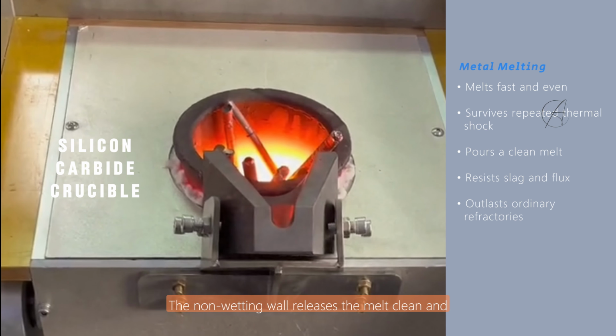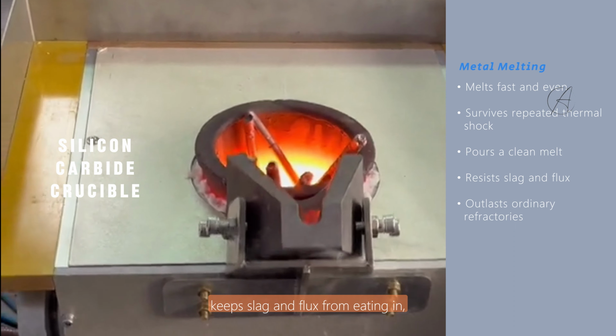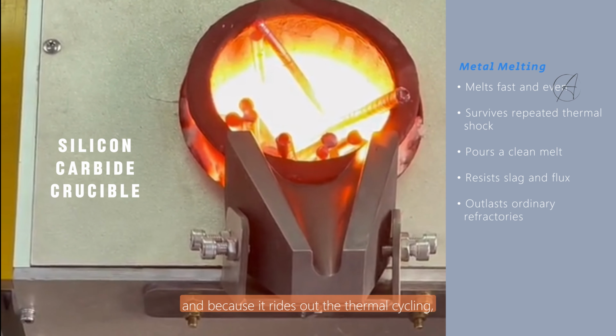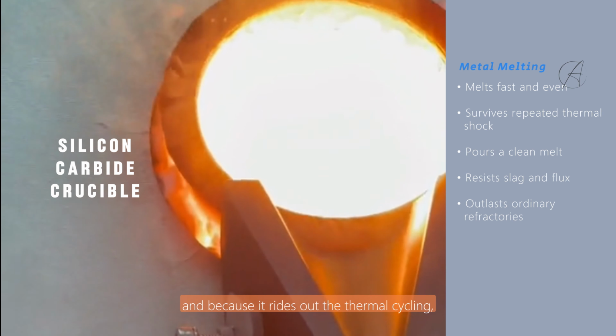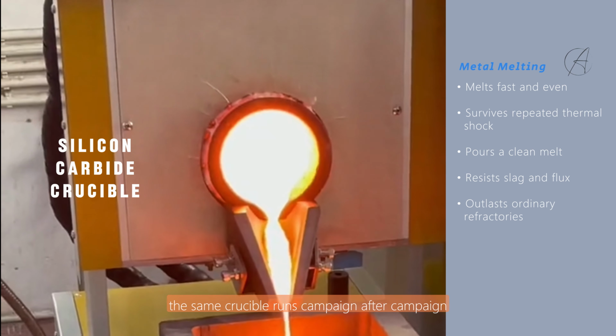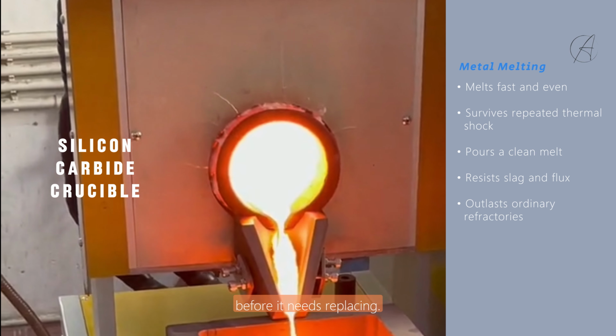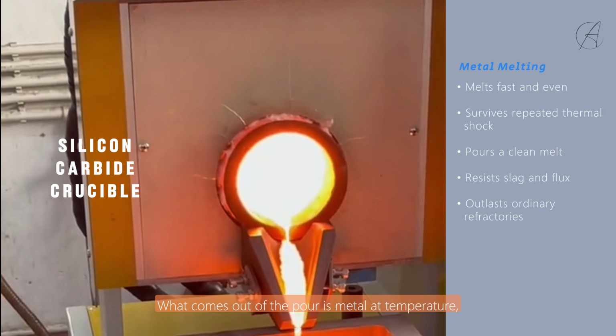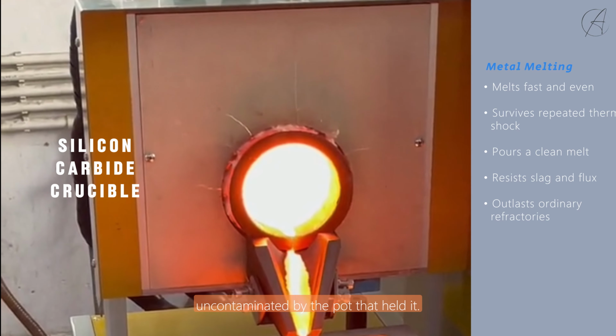The non-wetting wall releases the melt clean and keeps slag and flux from eating in, and because it rides out the thermal cycling, the same crucible runs campaign after campaign before it needs replacing. What comes out of the pour is metal at temperature, uncontaminated by the pot that held it.